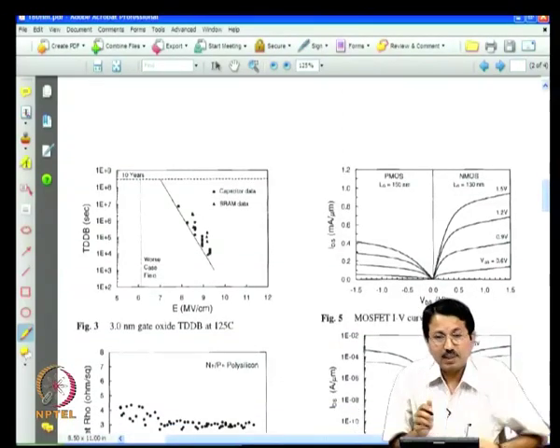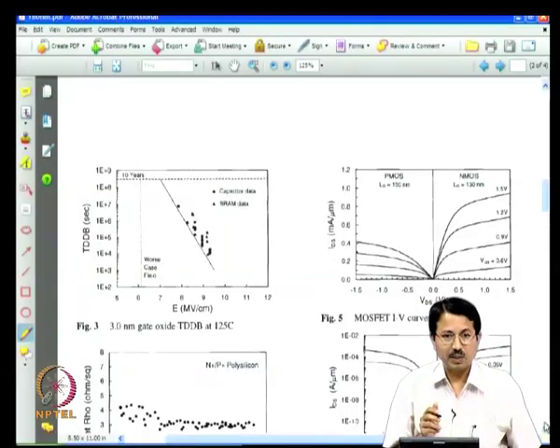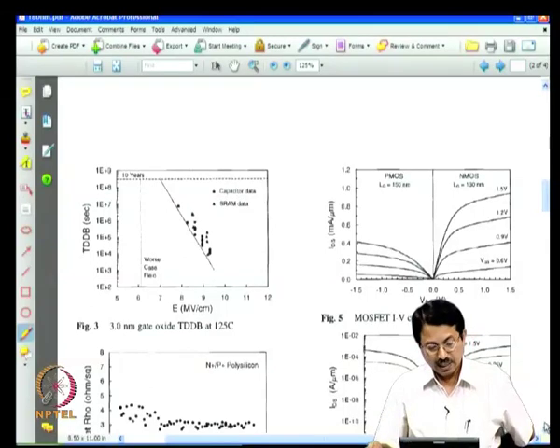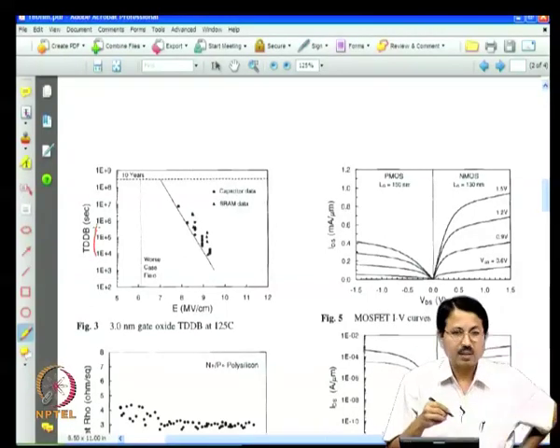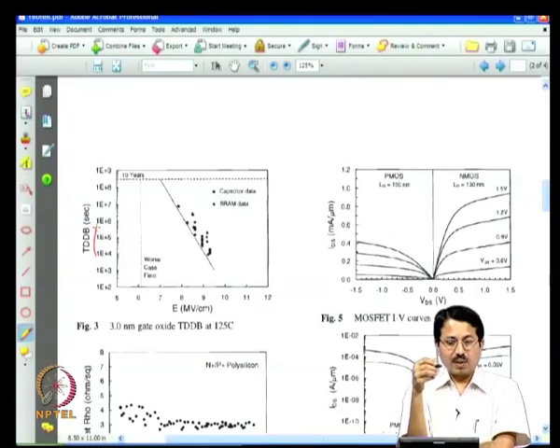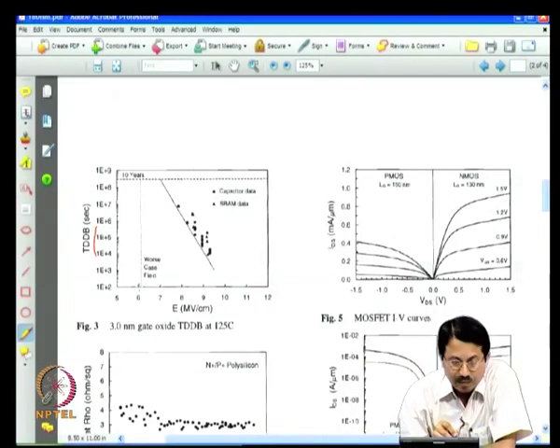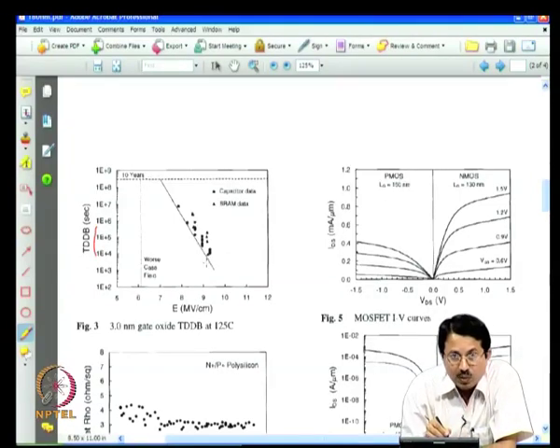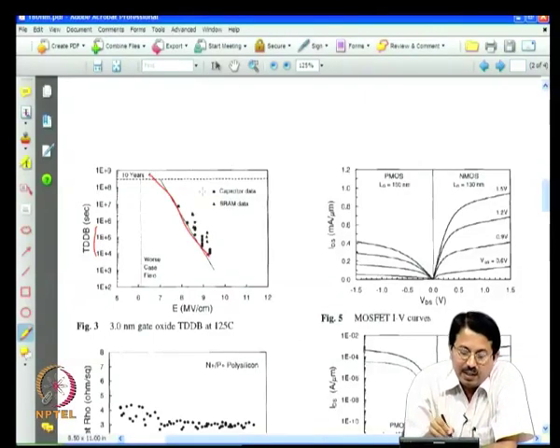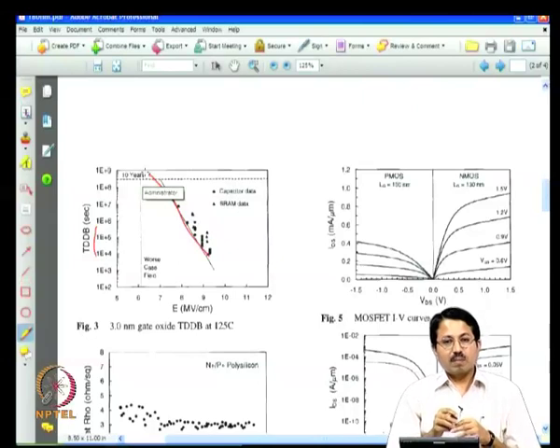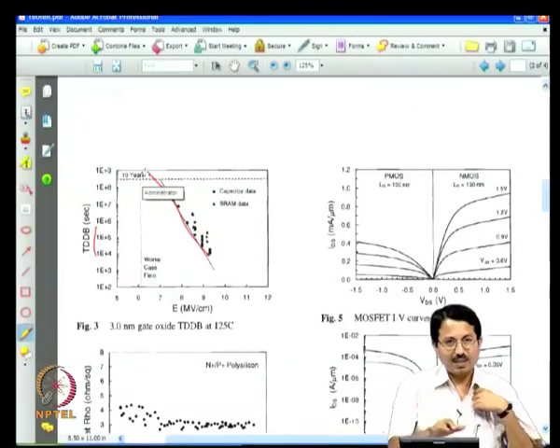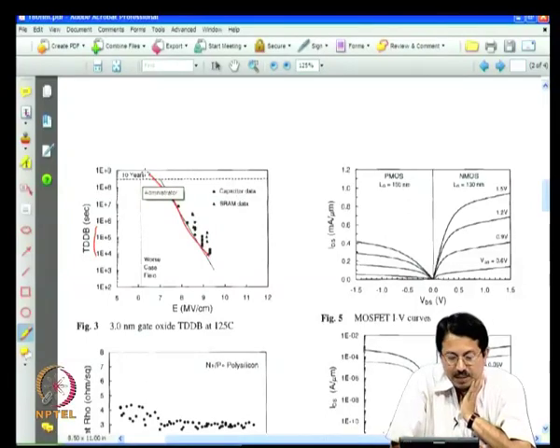One other important aspect that we had discussed, all these reliability issues. Remember, I said when you do the gate oxide reliability, there is something called TDDB, time dependent dielectric breakdown. Even though you are going to operate your transistor at very low electric field, such as maybe in this case 6 megavolt per centimeter, what you do is apply a large electric field and characterize the breakdown times, and based on that you extrapolate and say that in the real use condition this will be reliable up to 10 years. They have done a similar thing to what we have discussed. These are typical reliability characterizations.